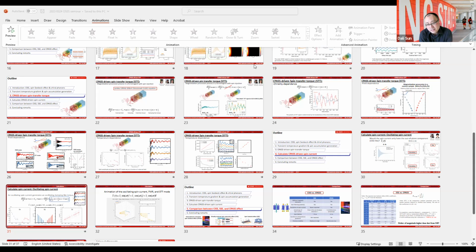For the first question, yes. We attended the APS March meeting. Some people believe the chiral phonon has an effective magnetic moment. Similar to magnons, from Raman spectroscopy they see the peak shift as a function of magnetic field, exactly like magnons, right? But this is in the chiral phonon, because the 2D material itself is non-magnetic. So yes, we can equivalently think the chiral phonon may be similar to magnons at the current stage, but maybe there are some other differences that I haven't noticed. I admit that it's very similar to magnons, just without the magnetic moment.